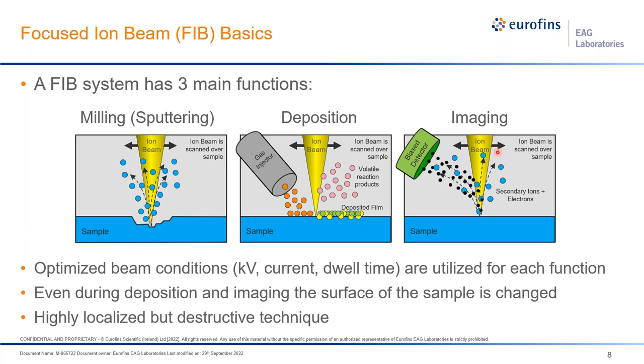There are unique benefits to imaging with FIB, as the interaction volume is much smaller with the ions than it is for electrons at the same energy. So the information in these images is even more surface sensitive. This even led to the creation of the helium ion microscope and its unique set of opportunities. So for each of these functions, we utilize an optimized set of beam conditions, but it's important to always remember that while FIB is highly localized, it's also a destructive technique, even under imaging conditions. And it's this fact that eventually led to the creation of the first FIB-SEM dual beam instruments.